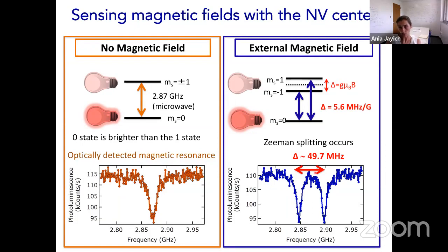fields. And again, if we take an ODMR, optically detected magnetic resonance spectrum, we see these 2 peaks in the photoluminescence as a function of frequency that spectroscopically identify these 2 transitions, and the splitting between them is proportional to the field. Okay, so that's kind of how the NV center works as a quantum sensor.